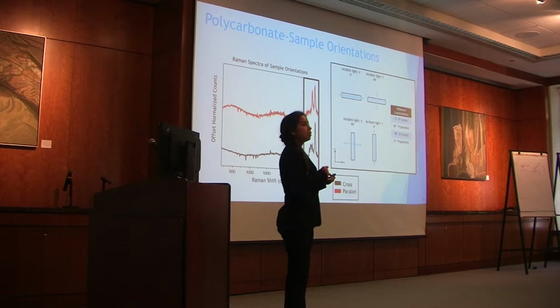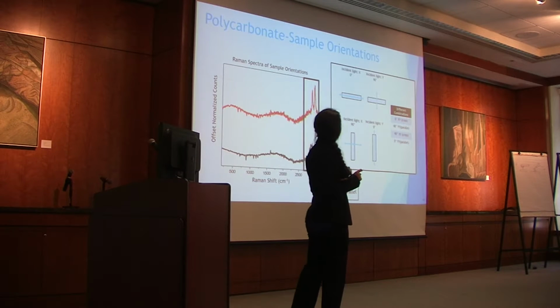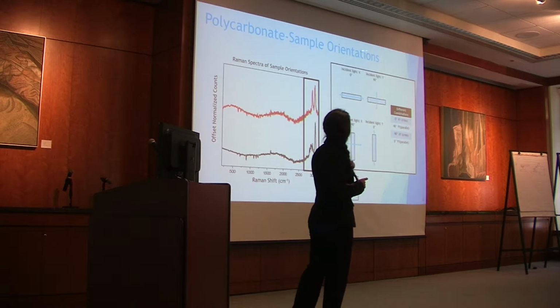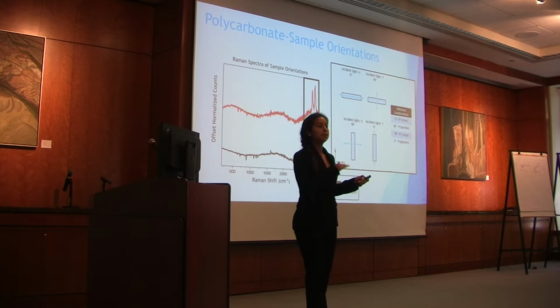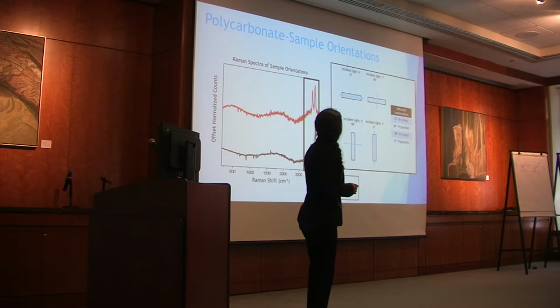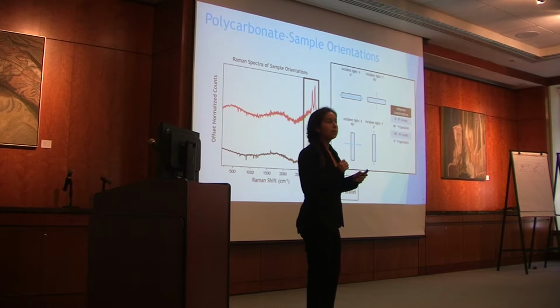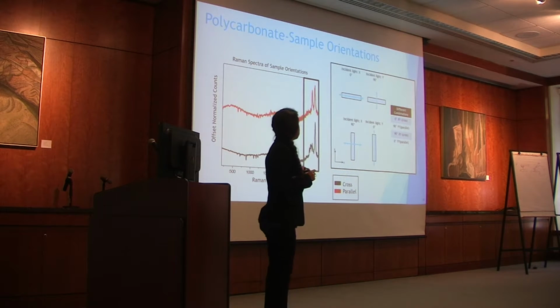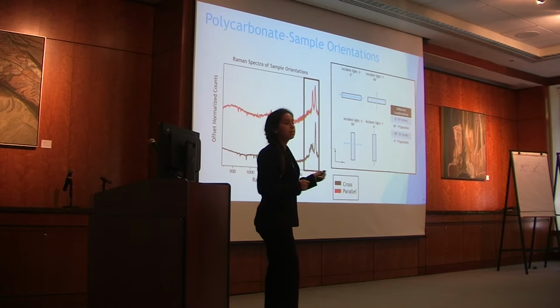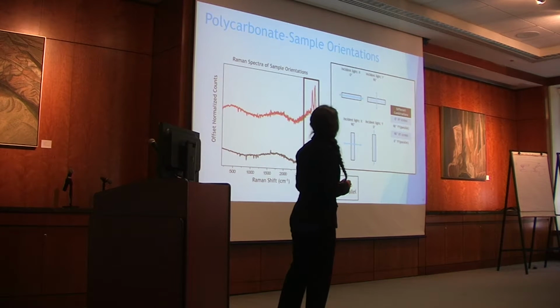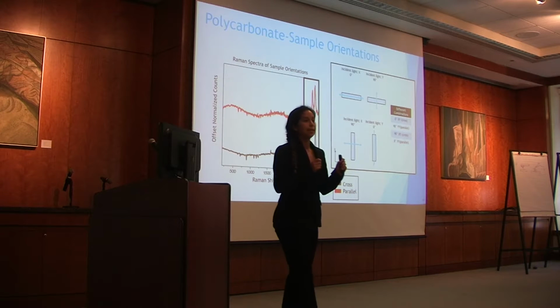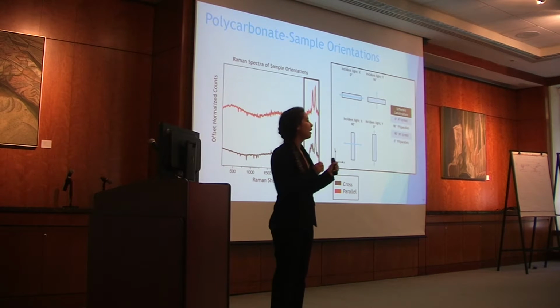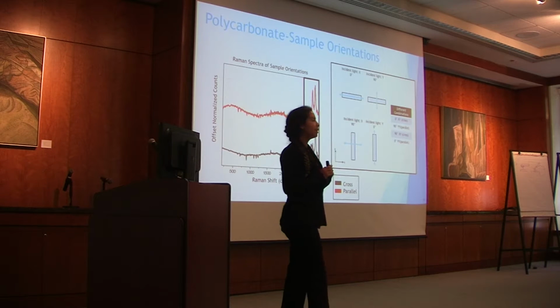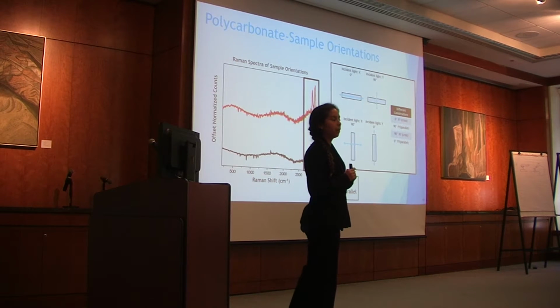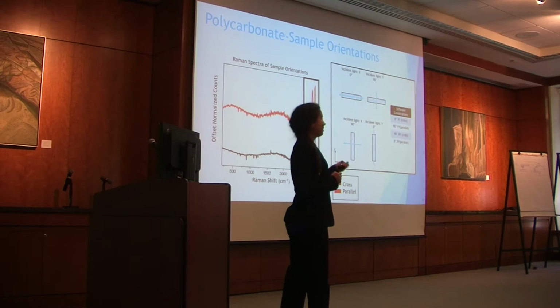In addition to looking at the change in incident light, we also looked at the change in the sample orientation. We aligned the sample across the X and the Y axis. When doing so, the spectra did look similar at first glance, but after doing a difference subtraction, X minus Y, we were able to see that there were still differences in the CH stretching region. This was very good news because, once again, it adds to this whole story of whether polarized Raman spectroscopy can help in understanding the molecular alignment of this polymer chain. And the answer is yes.